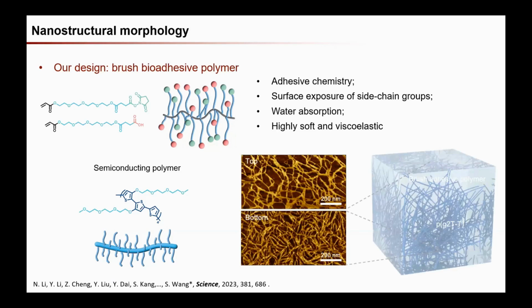Eventually, with this design, what we did is utilize these two monomers as a starting material to blend with the semiconducting polymer in the same solution, and then, with these still in the monomer state, spin coat into a thin film. In the thin film there will be some level of phase separation, but the monomer can help to reduce the phase separation scale. And then, after forming the thin film, we further cross-link this bioadhesive polymer under UV exposure. Eventually that gives us this kind of morphology, as shown by the AFM images.